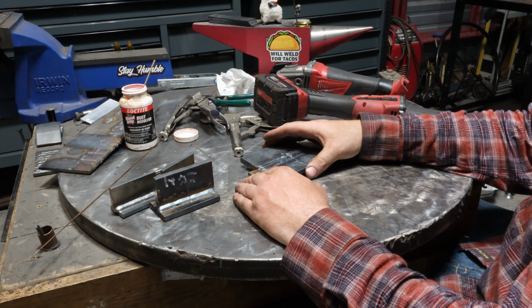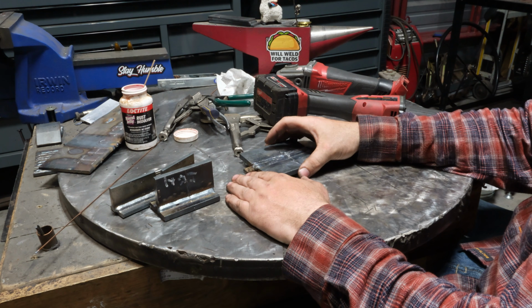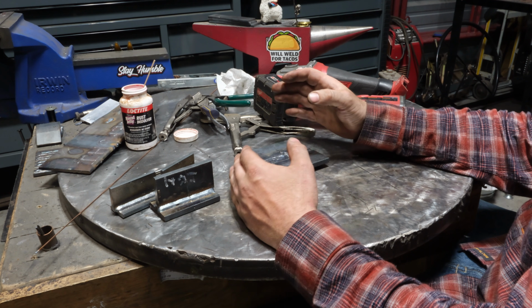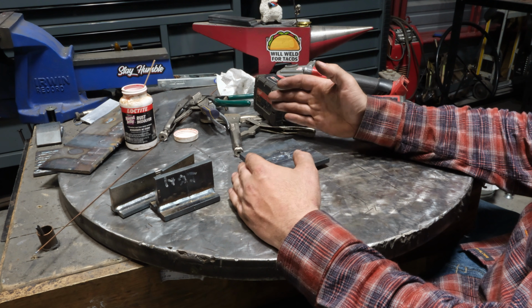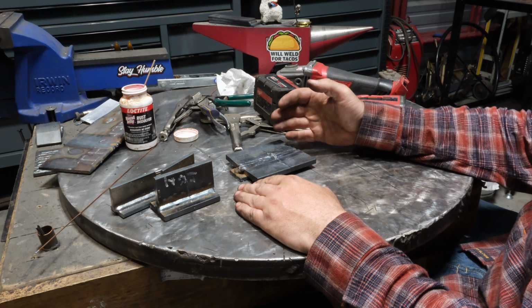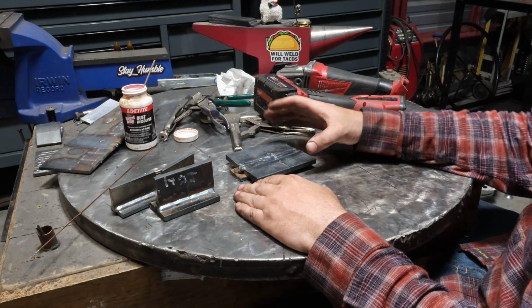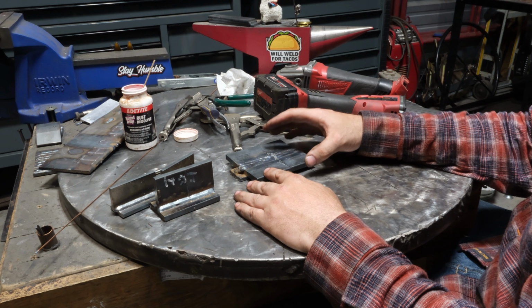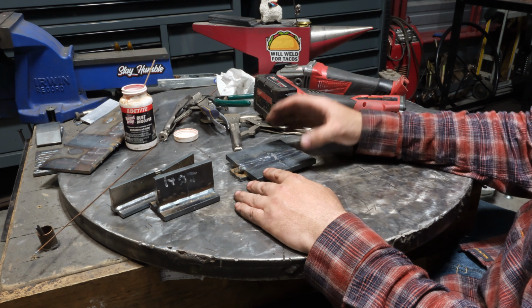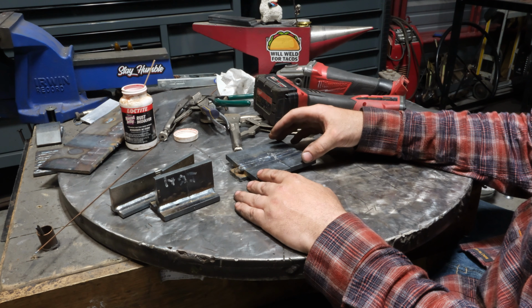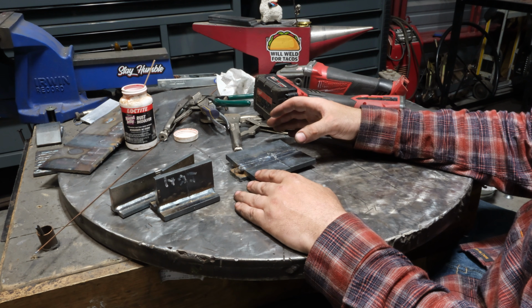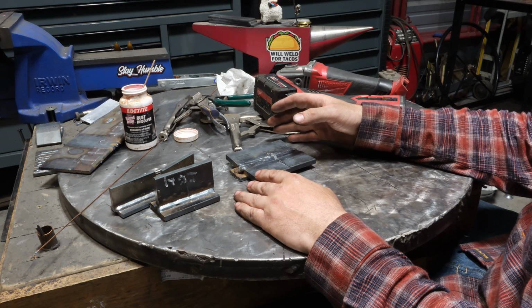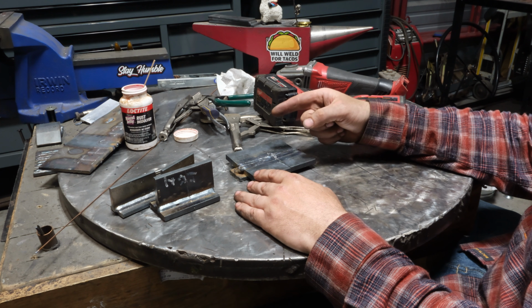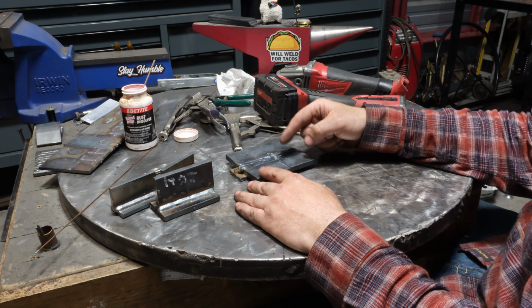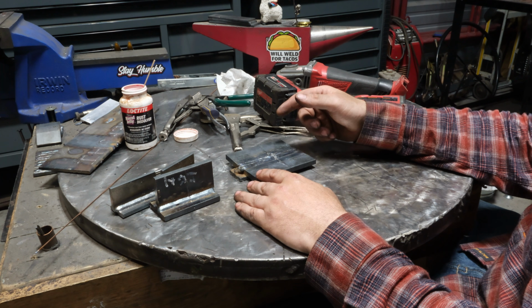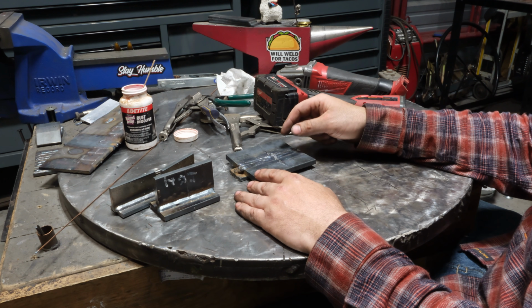So, what did we learn today? Well, we did a small experiment dealing with the short circuit MIG process and looked at results on varying thicknesses of material, and we had varying results. The key takeaway that I want to instill in you guys is that the short circuit MIG process is an extremely strong, reliable process when you have a properly sized welder, aka a 200 amp class machine. Because trust me, if you were attempting any of this with a 140 amp machine, I don't care if you preheated the steel to 2000 degrees, you wouldn't even get close to these results.